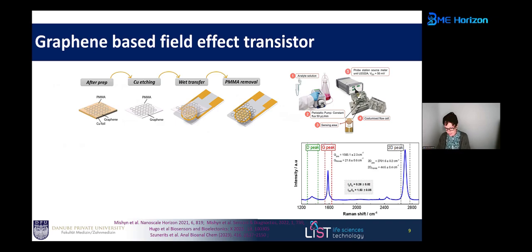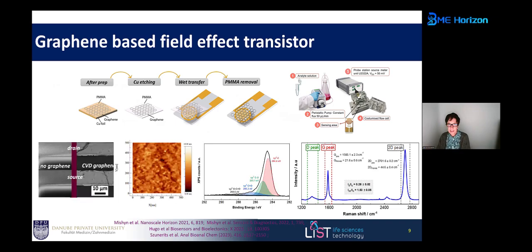You can buy these source meters, so you come to a point of care if you want, which is a benchtop based device. Now, when you do this graphene transfer, it's a wet transfer, so you have to put a polymer on the graphene so that it is mechanically stable enough, and then you print it on the surface. So it's very important that we have a full removal of this PMMA on the interface, otherwise we will not have access to graphene to do proper surface chemistry.